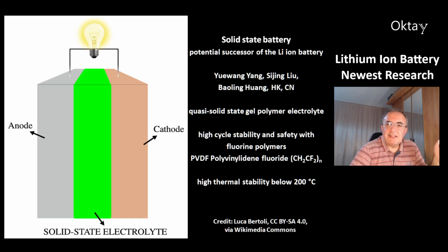This is another type of battery, that's a solid-state battery. It is a potential successor of the lithium-ion battery. There is a work of Yuewang, Sijing Liu, and Baoling Huang from Hong Kong, China. They made a quasi-solid-state gel-polymer electrolyte. This gives the battery high cycle stability and safety if you use fluorine polymers, for example PVDF, which is polyvinylidene fluoride, (CH2CF2)n. This gives this type of battery a high thermal stability below 200 degrees Celsius.